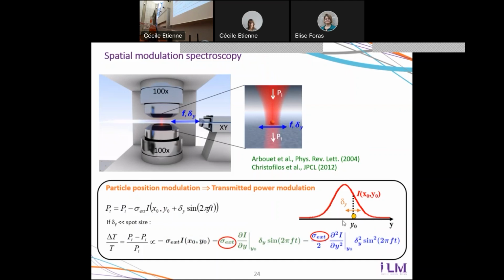Additionally, these components are proportional to the extinction cross-section of the particles through parameters which are related to the amplitude of the modulation process, which we can know, and to the distribution of the intensity of light in the focused beam, which we can also know. So from the signal that we measure, we can directly extract the extinction cross-section of the single nanoparticle that we investigate.